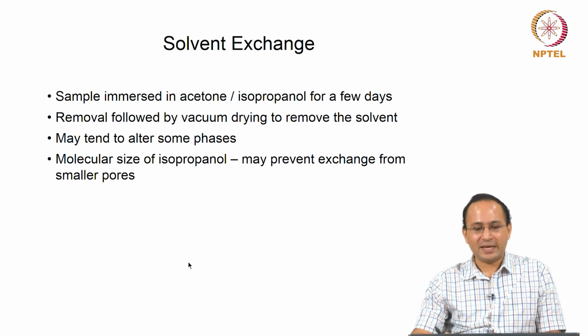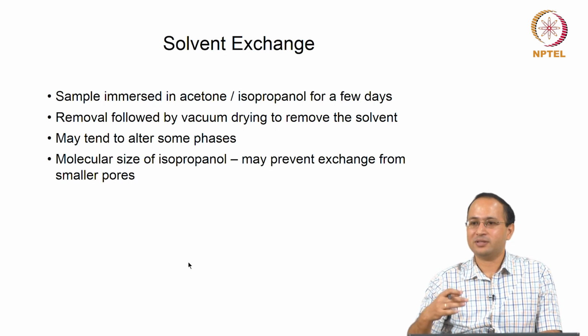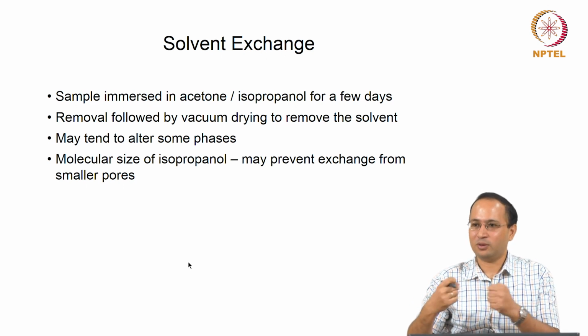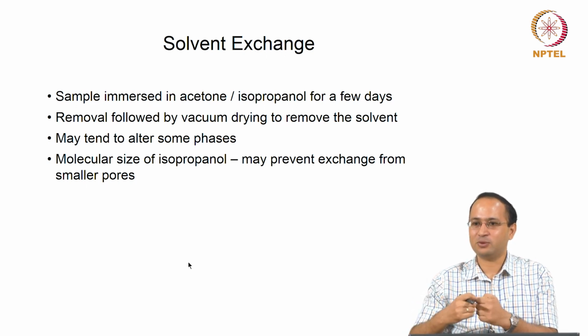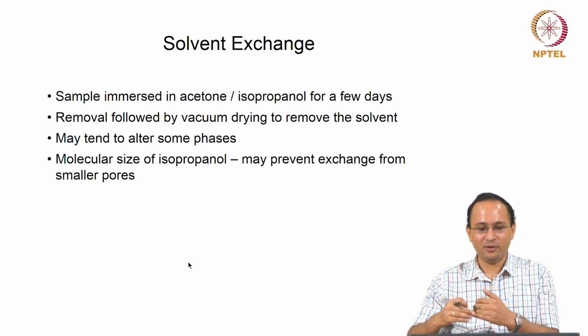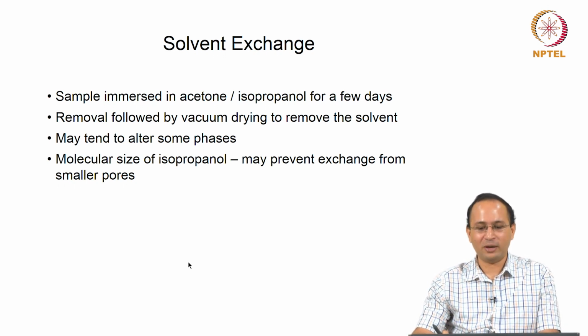The most commonly used technique is solvent exchange, right. So, the idea is we immerse samples in acetone or isopropanol for a few days. The alcohol will mix with water, these are miscible liquids, and then we use removal followed by vacuum drying to remove the solvent. Then we want to remove the solvent, right. So, let it evaporate. That way we remove the water also, but it may tend to alter some phases.